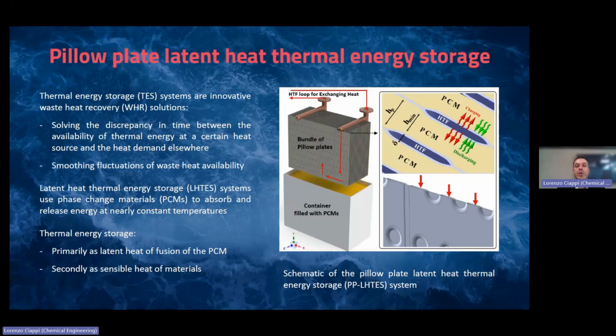The pillow plates comprise a bundle through the two manifolds and are submerged inside the phase change material that is contained inside the tank. The principle of operation of the system is the heat exchange between the heat transfer fluid and the phase change material. During the charging phase, the heat transfer fluid releases heat to the PCM, increasing its temperature, and the PCM, during the process of charging, stores heat. Conversely, during the discharging phase, it is the PCM that releases heat to the heat transfer fluid, completing this second phase.